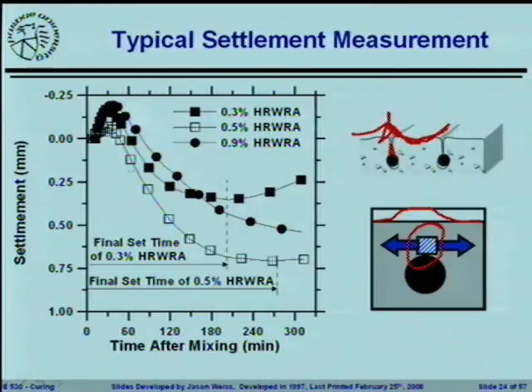bar. So one of the things that we tried to do is measure this with a non-contact laser. Again, remember you've got concrete that's settling, it's bleeding, so it's a little bit more complicated process. If the surface was going to stay where it's supposed to be, it would stay right at that red line that I've just drawn. Because of heat in the system, it's going to expand a little, and then you're going to see the concrete start to settle.